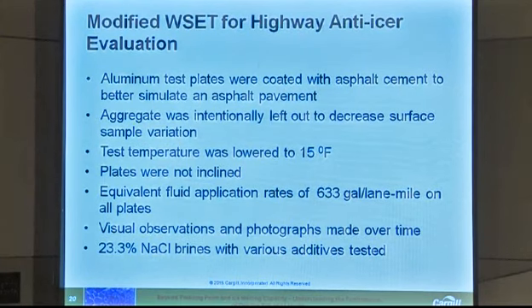We made the following modifications to better simulate highway de-icing. Instead of looking at bare aluminum, we coated the aluminum plates with asphalt cement to better simulate an asphalt road surface. We left aggregate out of the coating on purpose. We did some initial tests where we tried to use an actual real-life aggregate asphalt, but we had a lot of variability problems, and it cracked, and there was a number of test issues. So we settled on just using asphalt cement with the assumption that chemically the surface is going to be pretty much like an asphalt road surface is going to be.